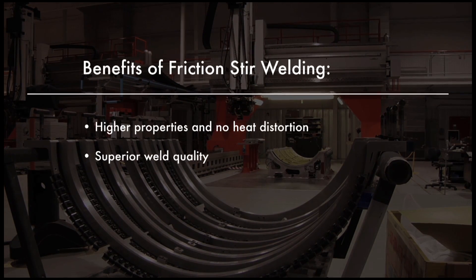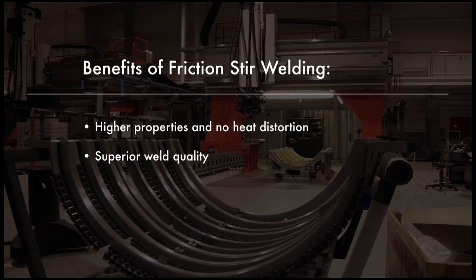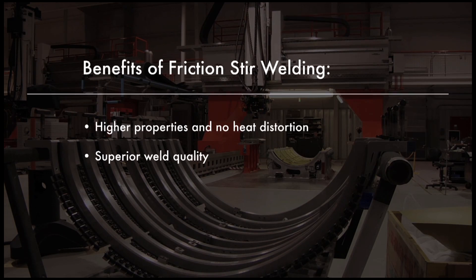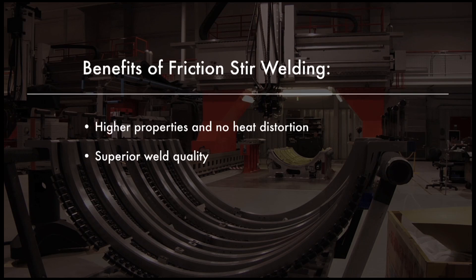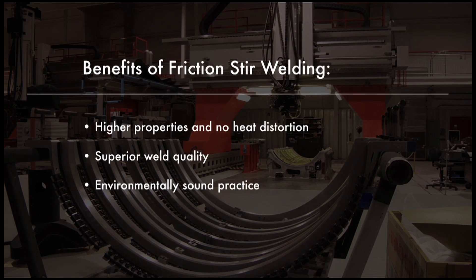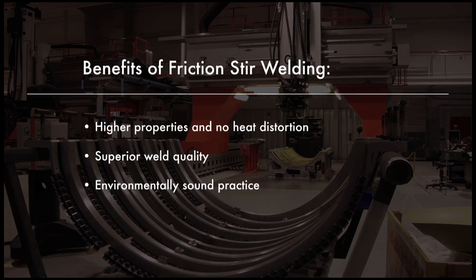The crushing, stirring, and forging action of the friction stir welding tool produces a joint with a finer microstructure than the parent material and twice the ultimate strength of traditional welded joints. Environmentally sound: friction stir welding produces no fumes, uses no gas or filler wire, and saves weight on the finished jet which directly affects the amount of fuel being used in flight.